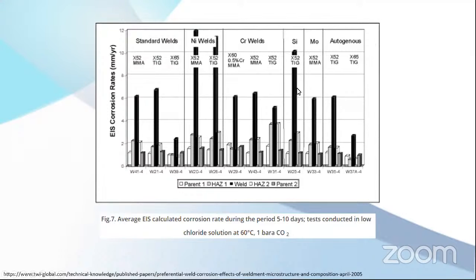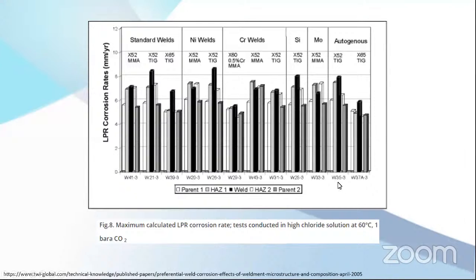With silicon, you also have very high corrosion. But this is the environment in low chloride solution, 60 degrees and 1 bar CO2. But if you change the environment, then it goes differently. This is high chloride with the same temperature and same CO2, but chloride is high, and you get similar corrosion rates. So as I said, it is unpredictable. So the best thing is just to use matching consumables.